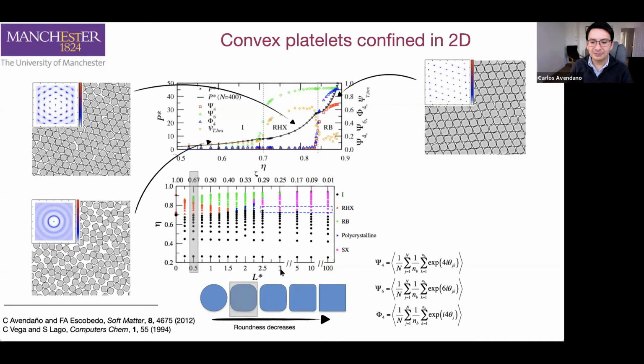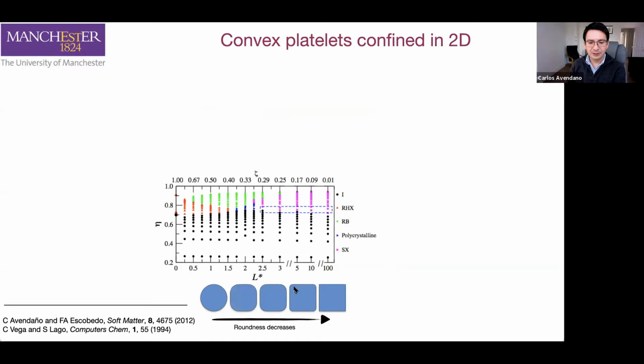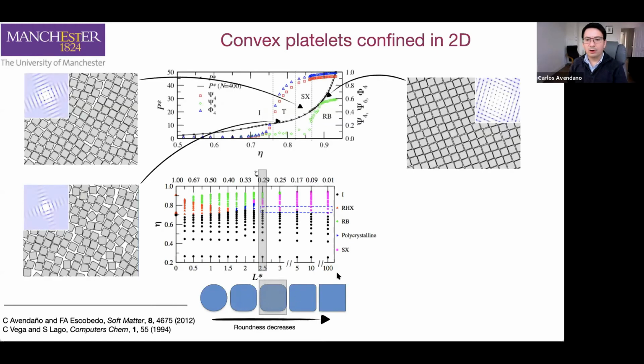So this allows us to conclude that that small change in the particle shape from the corners of the particle was enough to disrupt the phase behavior. We also analyzed squares in which the sharpness of the particles, or the corners, is a little higher than this system. And we observe exactly the same as the experiments. We observe formation of square faces, but also the formation of the rhombic faces. So again, this is just an example of how small changes in the particle shape could change completely the phase diagram of the systems.